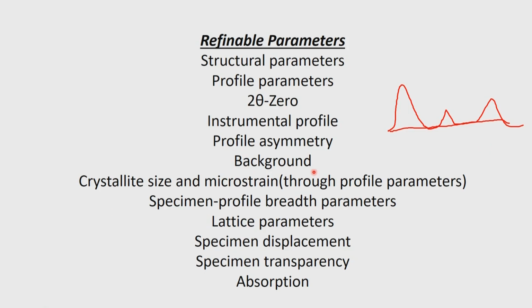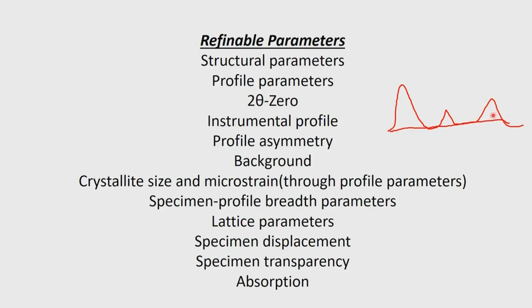How you account for the background will tell you how accurately you can get the peak positions and their intensities. Suppose you put the background way up here, then you lost all the reflections. So essentially background selection is a very crucial factor, and the way it is done is to choose the background along the 2 theta directions, starting from one of the low angle regions to the highest one, and choose some 20 or so points which are definitely not coming under any peak indication.